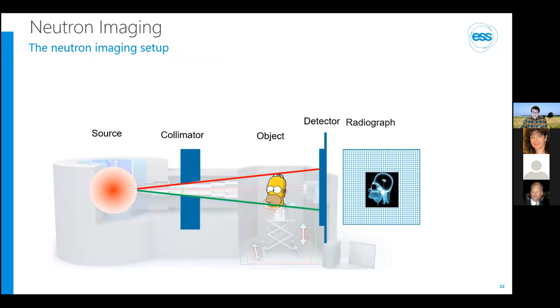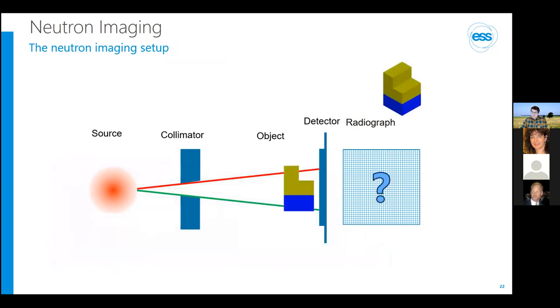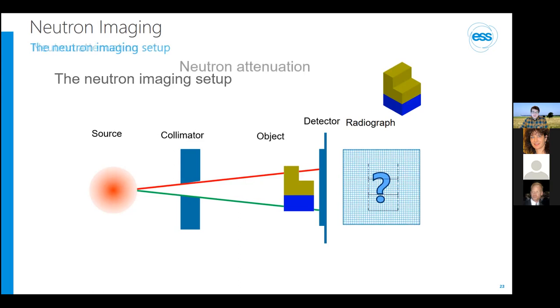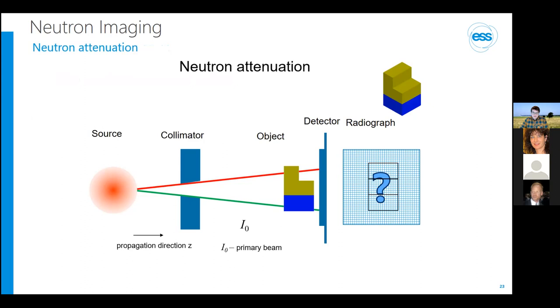So let us assume we now want to take a radiograph of this sample that is made from two different materials and has a varying thickness. So what will we see? Well, the neutron beam travels along the beam direction Z with an incident intensity denoted as I0 here. And the transmitted intensity on the detector, I, is then defined by what we call the Beer-Lambert law. Besides the incident intensity, it depends on the attenuation coefficient mu and the thickness of the sample Z.